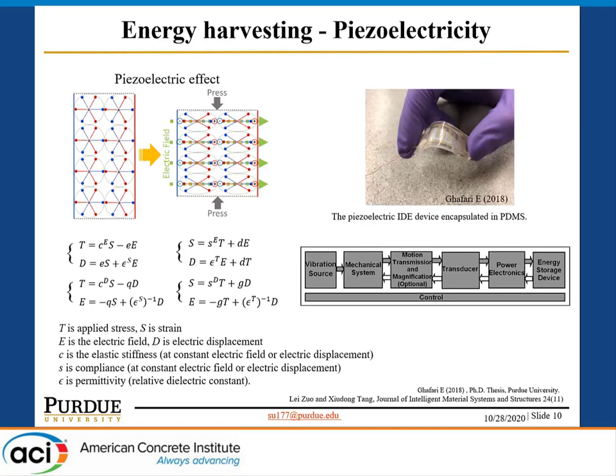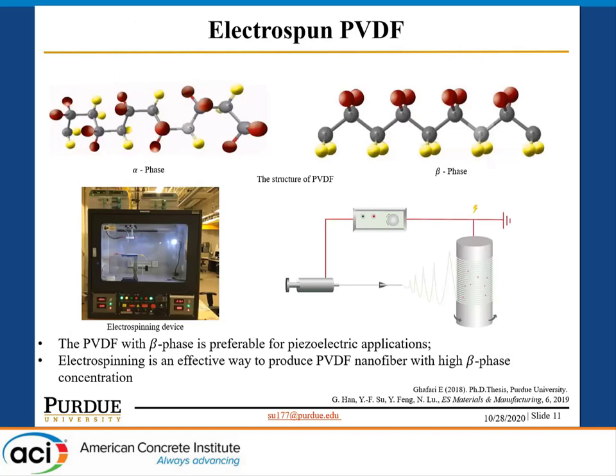And one of the promising piezoelectric materials is PVDF. PVDF is a polymer-based piezoelectric material, has very high flexibility, and can be adapted to different parts of the structure. So that's why we look into using PVDF. And in our lab, we use an electrospinning device to generate PVDF beta phase nanofiber and make it into a device and incorporate it into cementitious material.